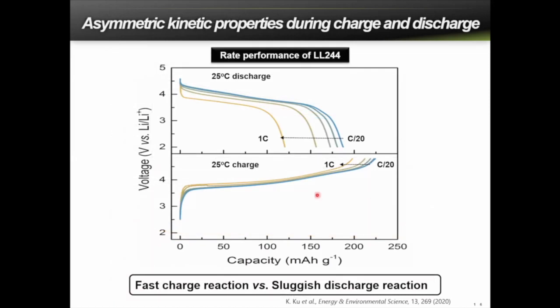And we found that this low power capability problem is not from the charging process, but interestingly from the discharge process. As we can see here, when we increase the current density during the charge from C/20 to 1C, the reduction of the capacity is not so notable, it's not significant. On the other hand, when the same experiment was conducted in the discharge, capacity reduction is much more appreciable. And it is a very interesting behavior and has not been observed in a conventional layered electrode material where the intercalation and deintercalation are regarded as symmetrically opposite reactions, so the behavior should be similar.